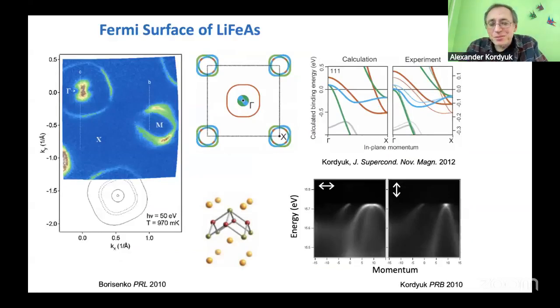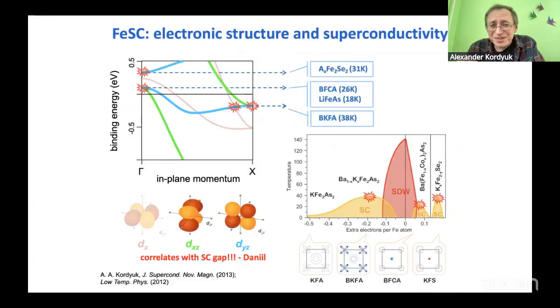But what is interesting and important about these compounds is that they are like a Lego constructor. You have similar bands. You have always these 5 bands, but in slightly different positions for different compounds, for different doping. With doping you could shift it, with pressure you could shift it, and you could find an empirical relation between electronic band structure and superconductivity. And we have found that it is very important that maximal TC appeared. You observe maximum TC when the top or the bottom of some important bands goes to Fermi level.